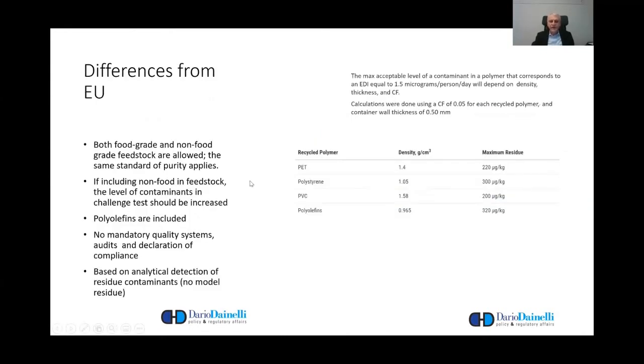produced. So the main difference from Europe, as I said, is in the assessment system. Here, you have a starting point consisting of the maximum acceptable level of contaminants in the polymer, which corresponds to the estimated daily intake equal to 1.5 micrograms per person per day. It depends on the type of polymer itself. So the density, the thickness, and the quantity of this particular polymer which would be in contact with the daily diet. So here you have a calculation which is made for different polymers. What is changing is the density of the polymer, and also the so-called consumption factors, or the fraction of any specific polymer which will enter in contact with the average daily diet.